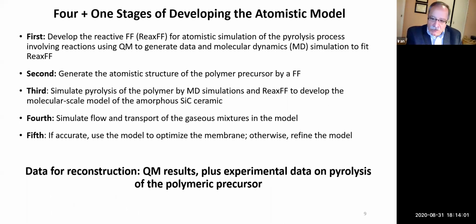We have 4+1 stages of developing the model. The first stage is we develop the reactive force field. We call it ReaxFF. And then we use that to generate quantum mechanical data in order to supply the reconstruction process to build the data. Then we generate the polymer itself. Then we simulate pyrolysis using that reactive force field. Eventually, we get the silicon carbide, nano-amorphous silicon carbide membrane layer. And then we simulate diffusion and flow through the membrane and look at the separation. And if it is accurate, then we try to vary the parameters of the simulation to see what is the optimal